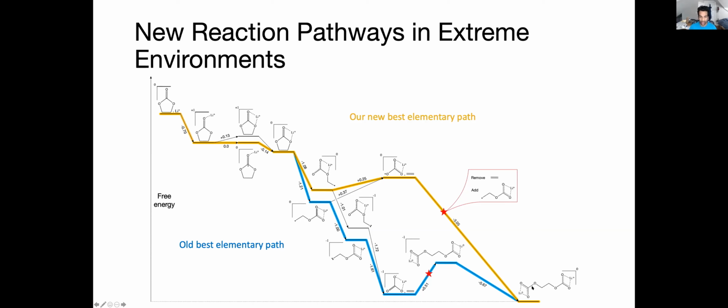Because we're not biasing ourselves to these exothermic steps, we were able to find with this reaction network a pathway that has a much smaller step in terms of going uphill in energy, but as a result, it's very easy for this intermediate to then transform into the LEDC. So we think this is a much more likely step of how an SEI is forming than what people have at least postulated in the past.